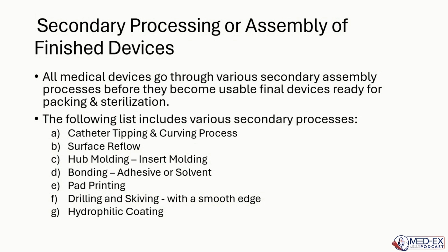And hydrophilic coating. Most of the cardiovascular catheters go through the hydrophilic coating process, and hydrophilic coating will adhere to the polar surface much better than any non-polar surface. So thermoplasticity and polarity really play a role in the secondary assembly to finishing of the devices.